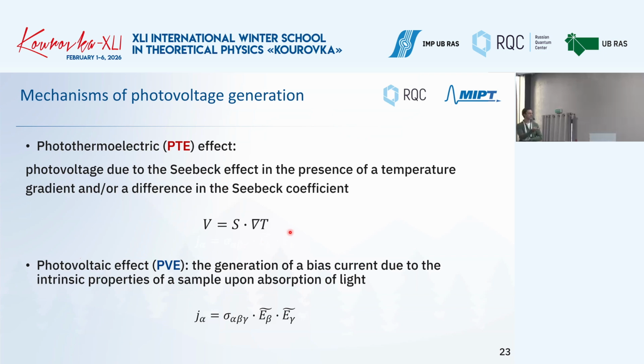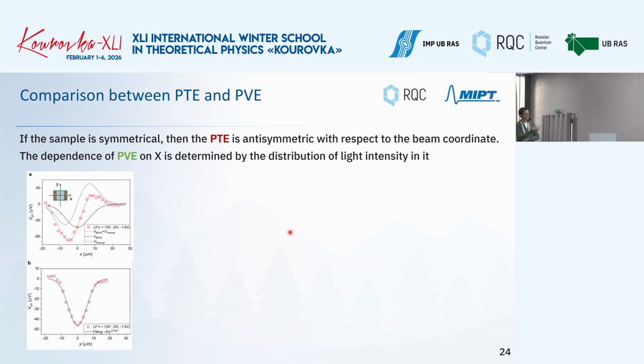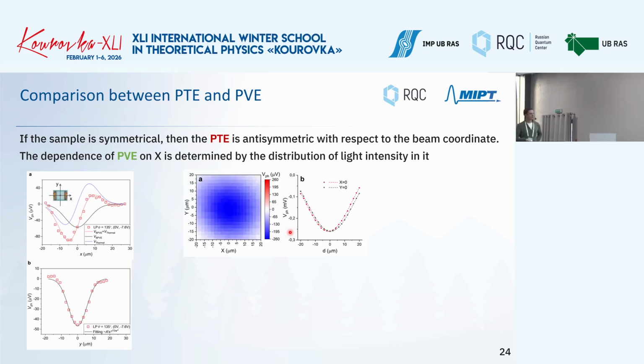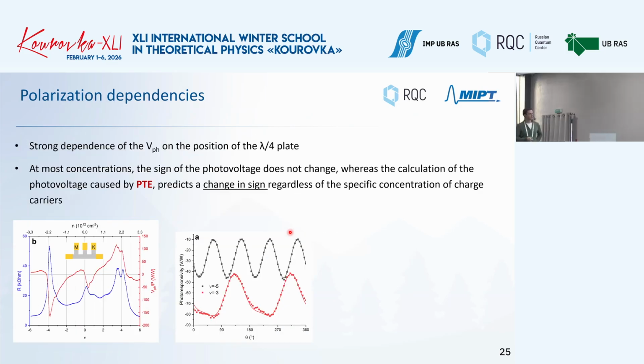And basically we tried to demonstrate, prove that this is the case. This can be proved by the dependence on the position of your light source. Then we do some experimental studies. We change the beam position. We go around and find out that probably the dependence is due to the photothermoelectric effect.